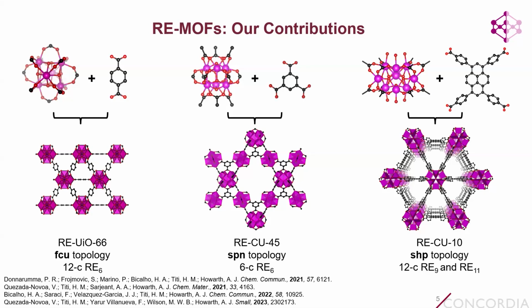And then we've also shown that you can make this MOF here that we call rare earth CU10. It has these nonanuclear cluster nodes bridged by the pyrene linkers and the overall SHP topology. And I'll talk more about this specific MOF in a few minutes. And so in all cases, we are able to make these metal organic frameworks using yttrium and then the lanthanoids ranging from gadolinium to lutetium, so the late lanthanoids.